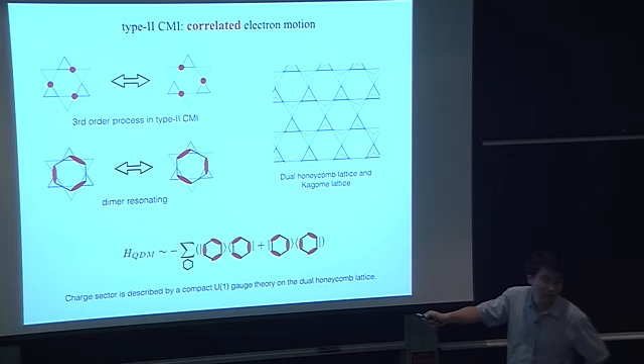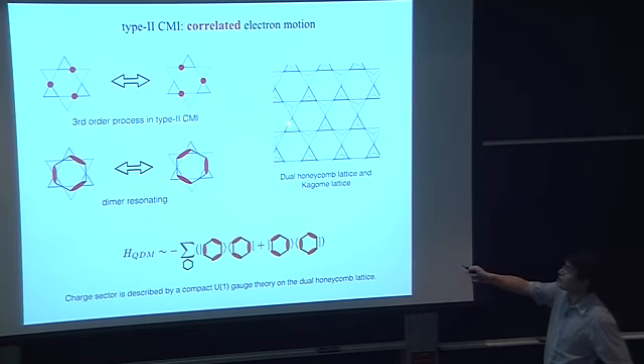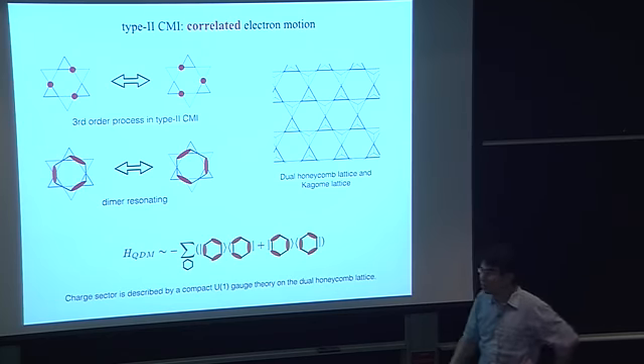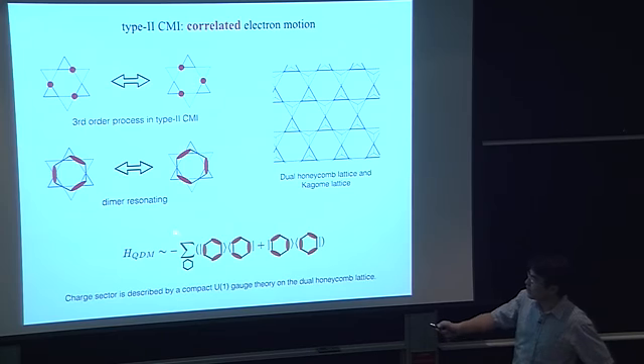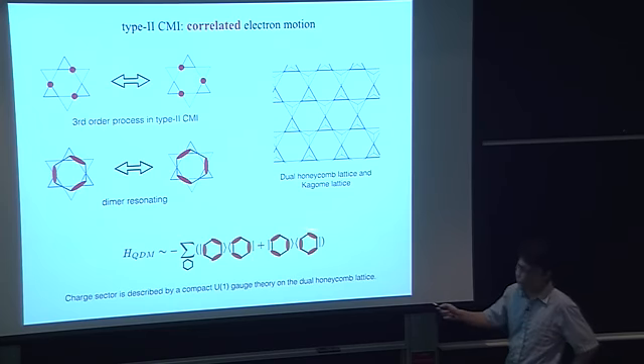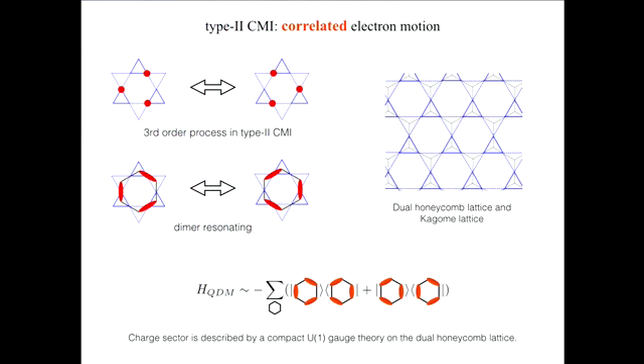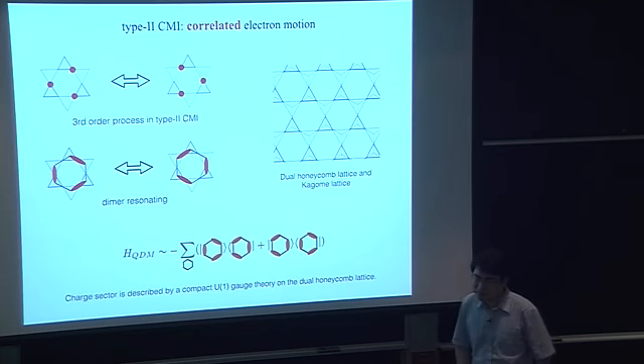center of each triangle, they will form a honeycomb lattice. It's a dual honeycomb lattice. So the low energy effective model is a quantum dimer model on a dual honeycomb lattice. This is the charge sector low energy Hamiltonian in the type 2 cluster Mott insulator. In fact, it's well known that the quantum dimer model on a bipartite lattice can be mapped into a compact U(1) gauge theory, like on a honeycomb lattice. I mean, Fradkin and Kivelson did it on the square lattice, which is bipartite. So this is the honeycomb lattice. It's not very different.